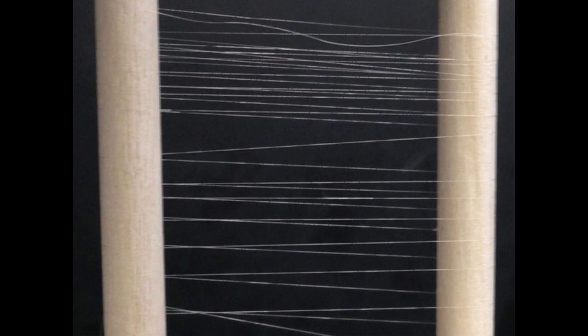To get around this longstanding obstacle, the researchers added a short genetic sequence to the silk DNA that promotes a chemical reaction between the resulting proteins, fusing them together to form an even bigger protein, bigger than has ever been produced and purified before.